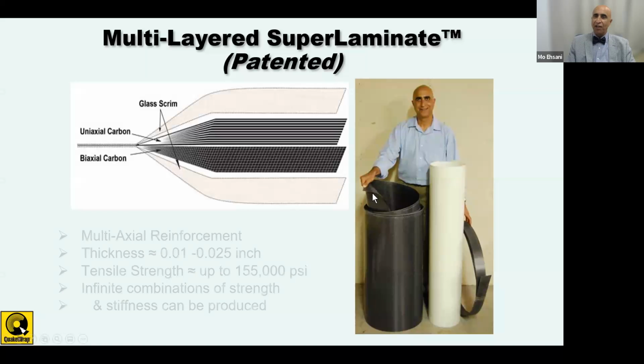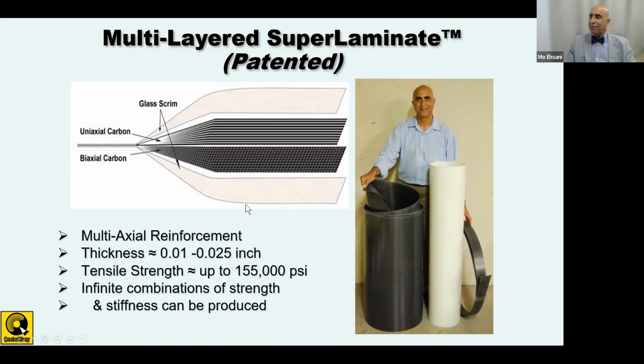Now what is unique about the laminate is that, as you see, it has enough rigidity. So unlike the fabric that is very flexible, these can kind of stand on their own, as you can see, but still they are very thin, so they can be twisted, as you see in my hand. Typically these laminates that we manufacture, the tensile strength is really high. We can make them as much as 155,000 PSI, but very thin, and that's the challenge of making these, is to make them so thin that allows us to apply them in some of these different applications that you'll see in a minute.